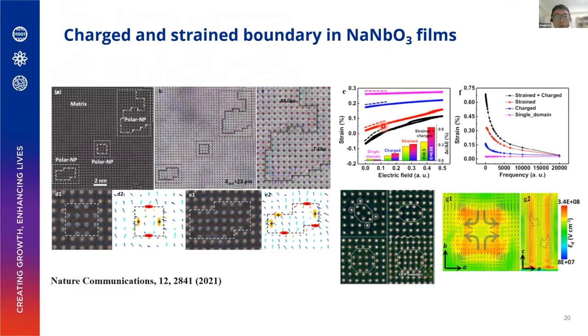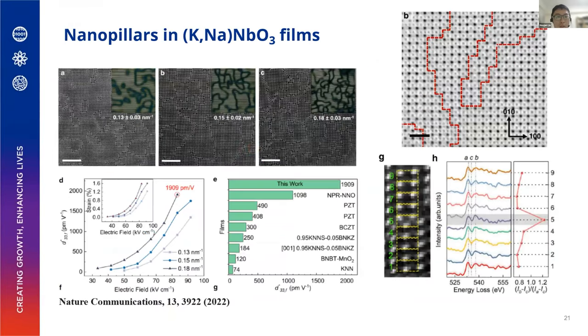Okay, then in the follow-up work, we actually look in more detail at the domains at the boundary between the pillars and the matrix. We see all different kinds of arrangements, and also some of them are charged and strained. And in another work, we looked at the effect of the density of these boundaries. So basically, when you have a high density, you can even further increase the piezoelectric response.